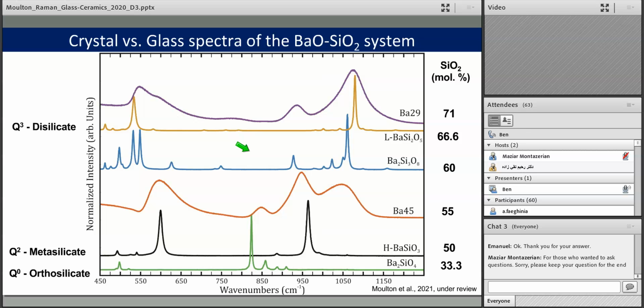I highly recommend people read the Brower and White article. If we broaden, that was an example of the metasilicate composition here at 50% silica. If we look at a compositional suite, this is in the barium silica system, which is from my current work, we see that the crystal structures here, the disilicate composition is composed of Q3s, the metasilicate here is Q2s, and here's the orthosilicate with Q0s. And in the high frequency region, we see strong peaks related to these structural units that sort of correlate similarly. They sort of bound the peaks in the glasses.